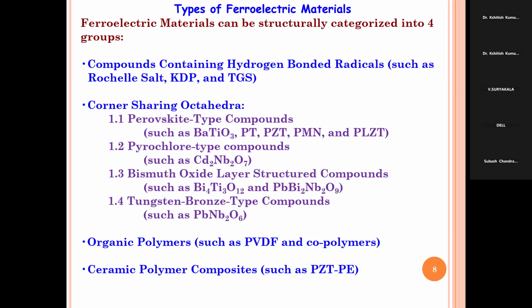And all of you know that barium titanate is the best ferroelectric material, and also PZT, PMN-PT, which are lead-based ferroelectric materials. Now, lead is poisonous, and for that research is going on into lead-free ferroelectric systems. So in barium titanate, from 1952 people have been working on the same material, doping on different sites, substituting different elements to get better properties.